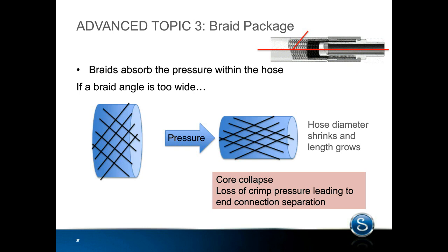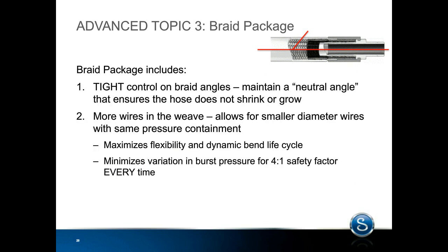So braid angle we found to be an extremely important factor in a braid package, and we do a lot of testing at Swagelok to maintain what we call a neutral braid angle. Every hose, depending on the braid material and the braid wire count and the hose diameter, has a different neutral angle, and we test that very closely to make sure that we maintain that neutral angle so that our hoses do not grow or shrink. The braid maintains pressure on the hose without allowing it to grow or shrink, therefore keeping our 4-to-1 burst and everyone's safe.